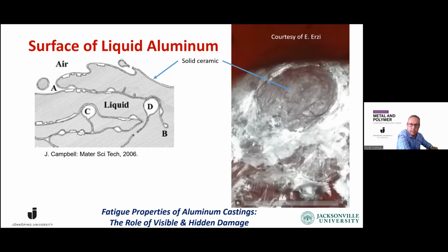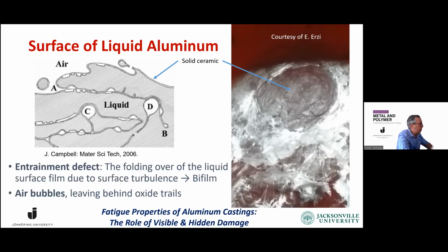And here you see a very coarse aluminum oxide, and we usually disturb the surface, and this results in the folding of this oxide, and it's being entrained in the body of the liquid metal. Because the solid to solid oxide contact creates no bonding, we effectively introduce cracks into the liquid metal, and these cracks find themselves into the casting, and after that they serve as cracks which affect the performance of our castings.